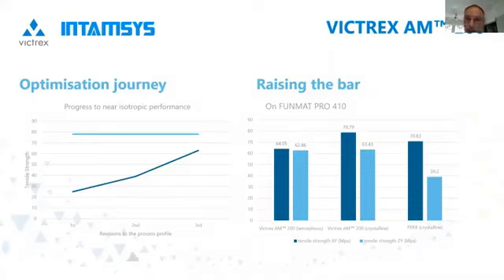In the center of the bar chart, you can see two bars for semi-crystalline AM200. And the main thing here being that the XY values are pushed that much higher to quite an impressive 78 megapascals, whilst the Z is around the same value that we saw for amorphous. And then the two bars that you see on the right-hand side are a benchmark reference for PEEK, which you can see is lower in the Z-axis there.